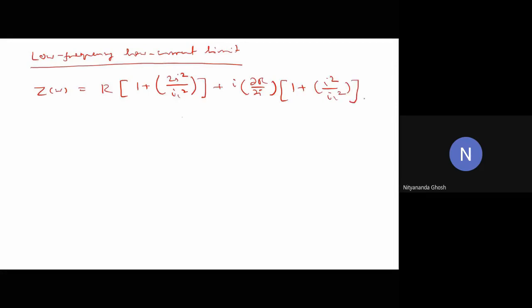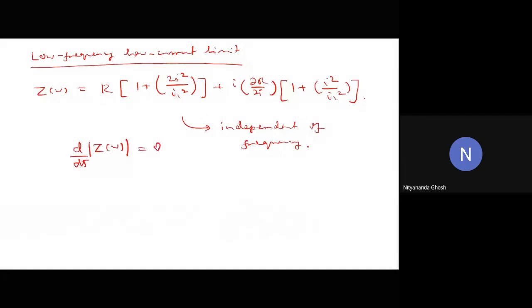And this is independent of frequency. So typical bolometric experiments using superconducting films as the active or absorber element are done in this low frequency, low current regime. If we plot Z against temperature, these curves will show an initial rise and then a decrease, just as we plotted during this class. And the existence and location of this peak could be found by doing d by dT of Z omega equals 0, and that would lead us to an expression